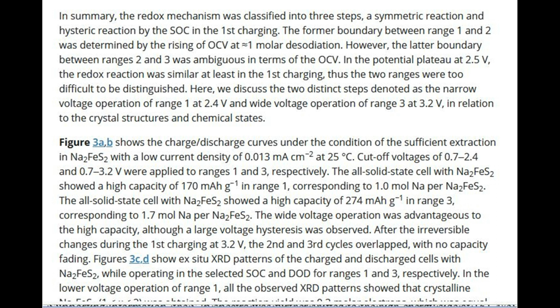In the potential plateau at 2.5 V, the redox reaction was similar at least in the first charging, thus the two ranges were too difficult to be distinguished. Here, we discuss the two distinct steps denoted as the narrow voltage operation of range 1 at 2.4 V and wide voltage operation of range 3 at 3.2 V, in relation to the crystal structures and chemical states.